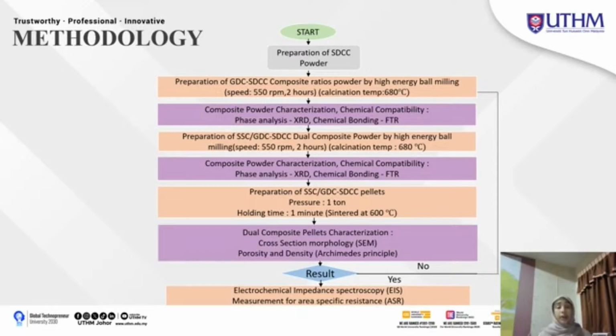And here we have preparation of SSC, GDC, SDCC pellets. So these pellets will go through a pressure of 1 ton, holding time 1 minute, and sintered at 600 degrees Celsius. So next is dual composite pellet characterizations. We'll go through cross-section morphology, SEM, and porosity and density, which is the Archimedes principle. And here there will be a little bit about the calculations that will give me numbers for the porosity and density using the Archimedes principle.